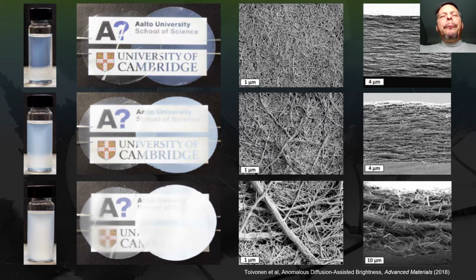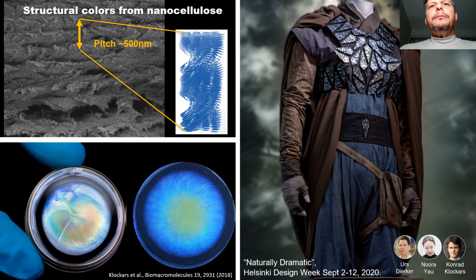And already here you can appreciate that the fact that light scattering is so different for these different materials is because the type of entanglement between the fibers and the porosity is quite different, and that can be controlled by fractionation. So my point so far is fractionation is extremely important for paper products, and I would say that this also includes tissue paper. And already here we are seeing the case of smart fibers in the sense that we can control light transmission and light scattering.